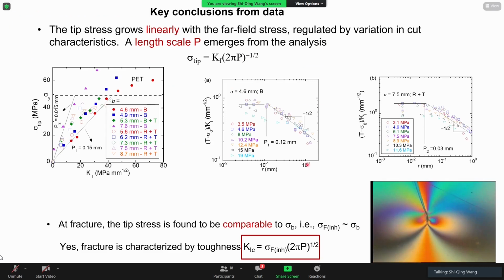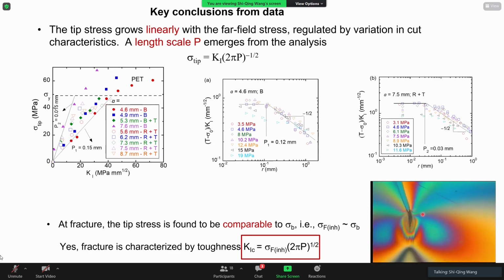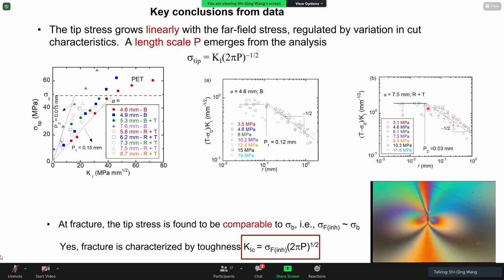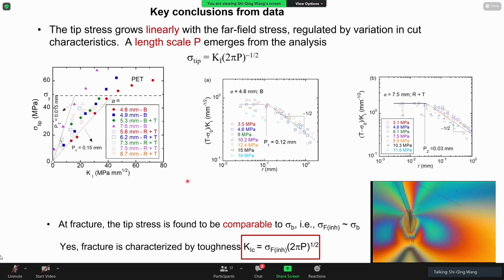This is just a movie showing the PET cutting. In fact, we can borrow this PET to illustrate the fact that the case changes because this stress saturation zone is different, depending on how we prepare the cut. So when you make a cut, you naturally involve some damage mechanics that cause some natural bluntness in your sample. And that controls how stress builds and where it saturates. As a consequence, you build to different levels of Kc.